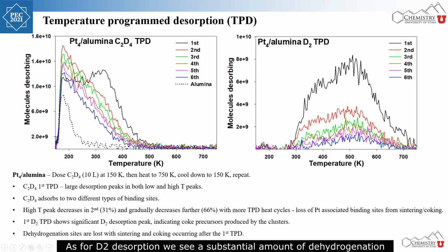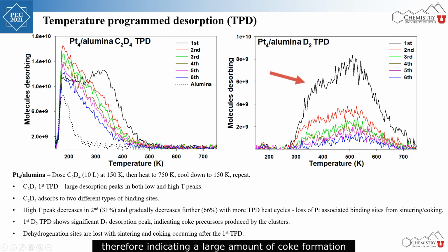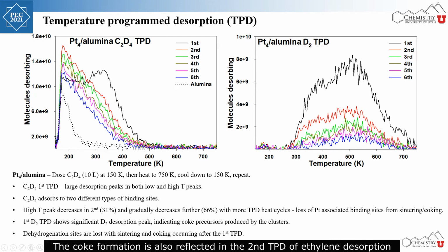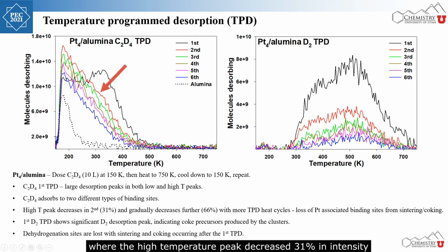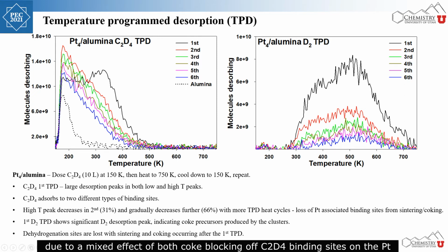As for D2 desorption, we see a substantial amount of dehydrogenation, therefore indicating a large amount of coke formation. The coke formation is also reflected in the second TPD of ethylene desorption, where the high temperature peak decreased by 31% in intensity due to a mixed effect of both coke blocking off C2D4 binding sites on the platinum and the platinum clusters sintering at the same time because of heating.